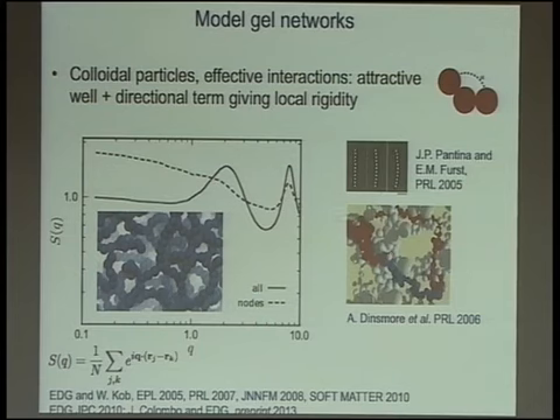And in fact, the fact that this type of simple colloidal structure does have a local angular rigidity has been measured in experiments in various ways. And for example, also the fact itself that you form this colloidal network at relatively low volume fraction, which have a typically local coordination number that is fairly low, between 3 and 4, does support the idea that you do have a small local rigidity that helps stabilizing this type of open gel structure.